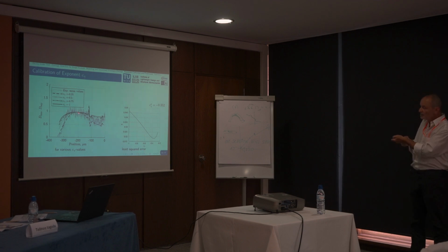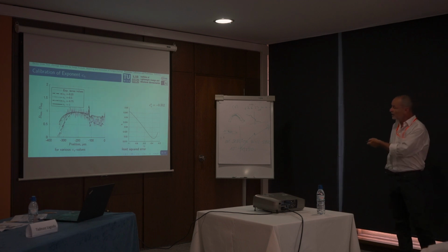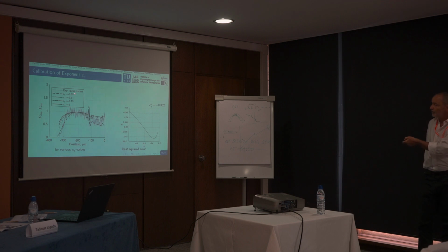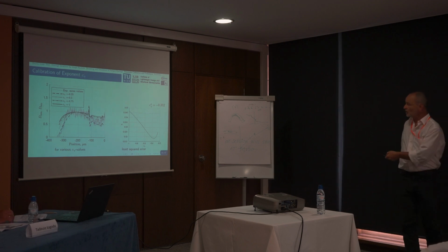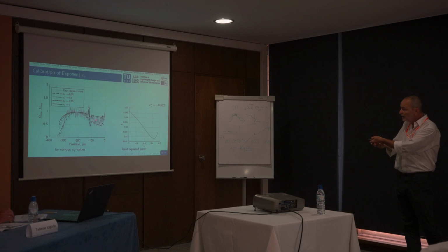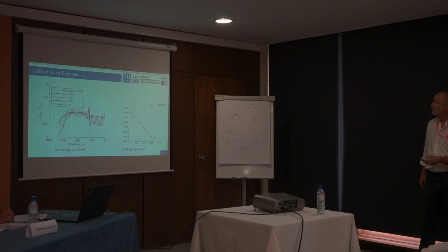They are all hinged on this point because this was the point where we have normalized those. But you can change the influence of the lifetime. And we do a least squares estimation of these values, and it turns out that the exponent of minus 0.35 has the best fit, somewhere between the dotted and the dashed line. So we can fit the exponent.